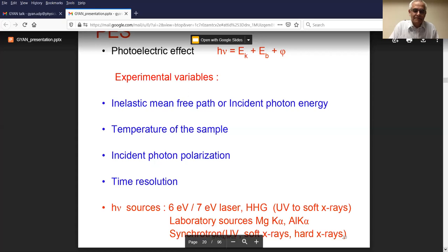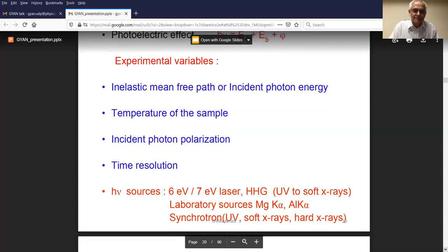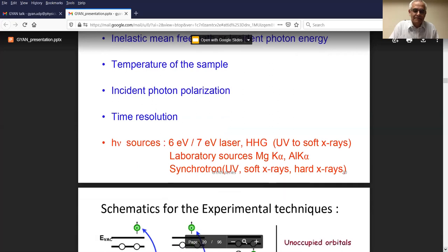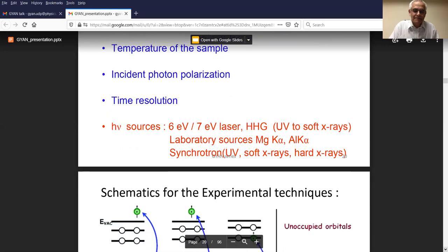More recently, people have started using photon sources which are low energy lasers, or even high harmonic generation lasers, which can range from ultraviolet to soft X-rays. All these things can be lab sources, including soft X-ray sources like magnesium K-alpha and aluminum K-alpha. Synchrotron is important because you not only get energies of different photons, but you can actually tune them while doing the experiment, which is not possible in other lasers or laboratory sources. This tunability is a big help.